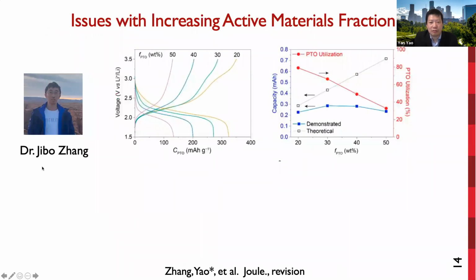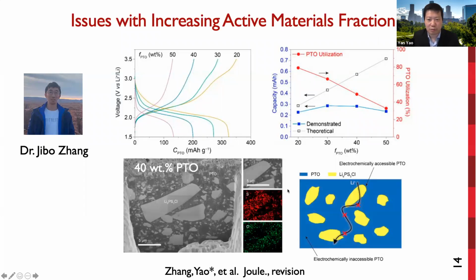So Dr. Jibo Zhang took the challenge to increase the PTO mass fraction. Jibo found that while increasing the PTO fraction from 20 to 50%, specific capacity decreased quickly. This corresponds to utilization from 80% to 32%. So in other words, the capacity didn't scale with PTO ratio following this theoretical line, but reached a plateau and did not further increase. Jibo found the origin of this low utilization is due to the unfavorable microstructure.